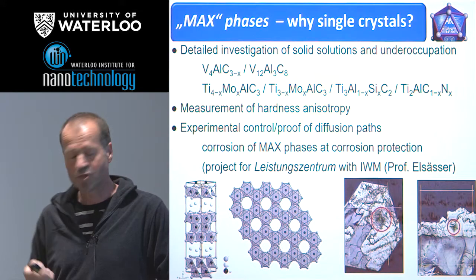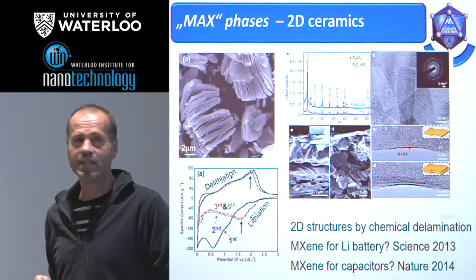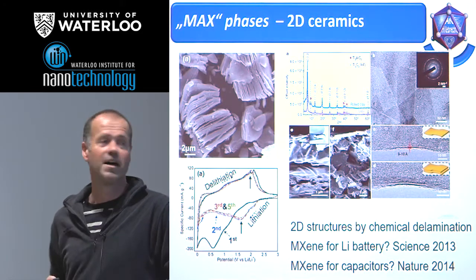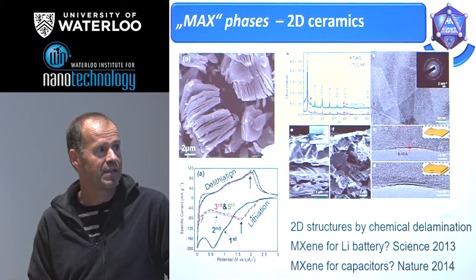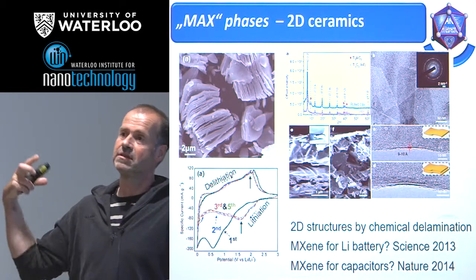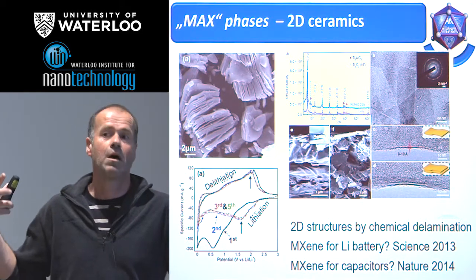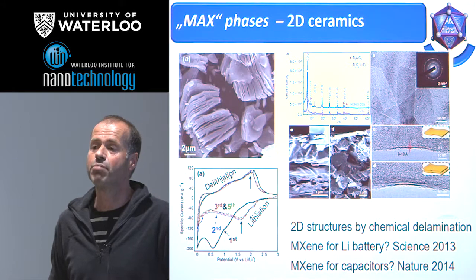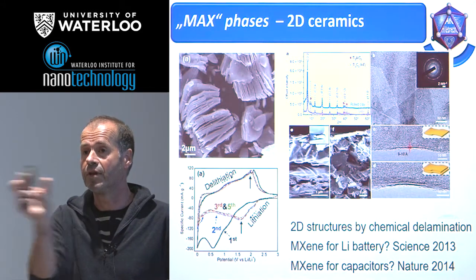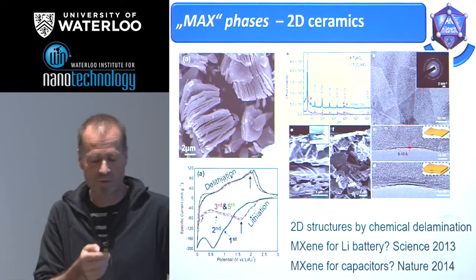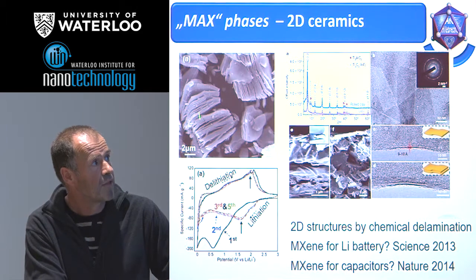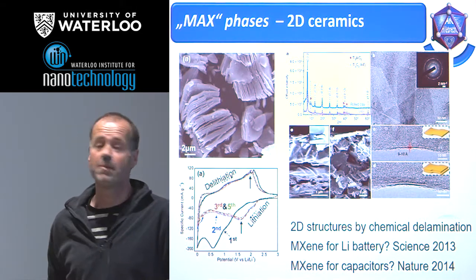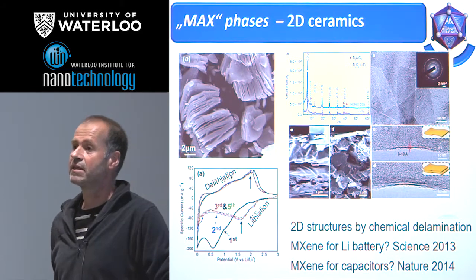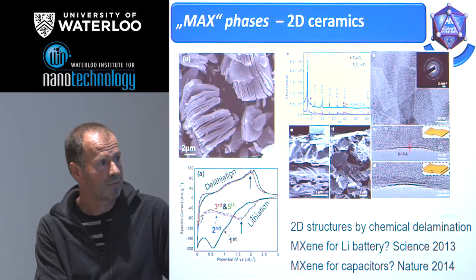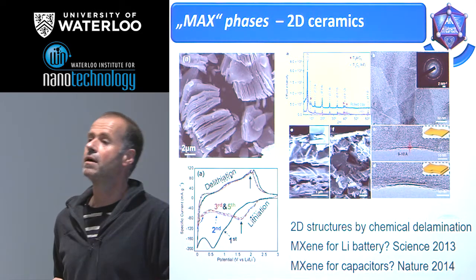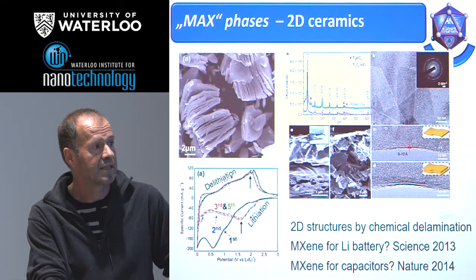We are not yet finished with the project, but later on there were some very interesting contributions from the large MAX phase society, and they could show that by a chemical delamination, that means by exposure to hydrofluoric acid, you can remove a part or completely the main group elements from these two-dimensional systems. You see from the pictures in the electron microscope that you get a delamination of these two-dimensional systems, and you have something more or less like graphene. And it was shown that these are interesting materials for the lithium battery, or they can be used as capacitors.